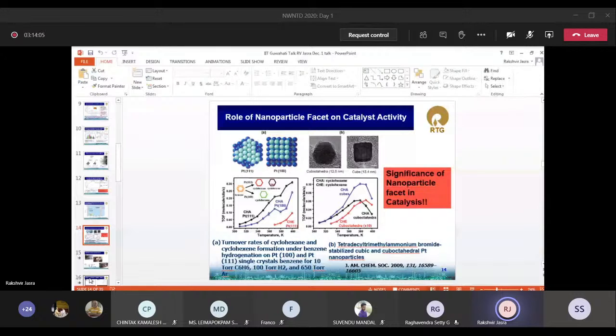So when I'm making a catalyst, if I want cyclohexane to be formed, it is very important that my platinum should be in a certain nano range, it should be in a certain shape, and also that desired facet should be maximized, exposed to the reactant. Second example is, again for the same reaction, two shapes, cube or octahedra. Now, if you have cubo-octahedra, then you can get some cyclohexene. But if it is only cubes, you don't get cyclohexene.